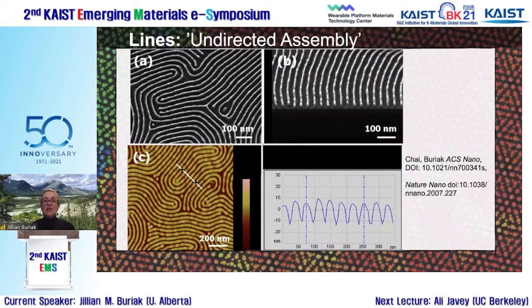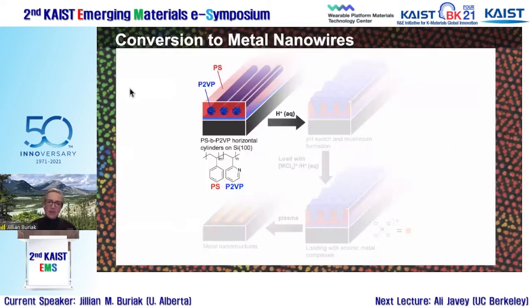Okay, so when we first got into this, there wasn't really that much work in transforming these polymers, which of course are plastics, into functional materials. And so we first came up with a way of being able to transform a particular block of polymer, this is polystyrene polyvinyl pyridine, into metallic structures. And so you could convert them into metal wires, depending on which block copolymer morphology you were interested in. Okay, we're making a single layer on a surface. These are platinum, but you can turn them into iron, into cobalt, into gold, into silver, basically whatever transition metal that you wanted. And so when you look at these, you say, okay, that's fine. You know, I can see these have a center to center spacing of 36 nanometers, but you don't have any long range order. And so I'll get into that in just a second.